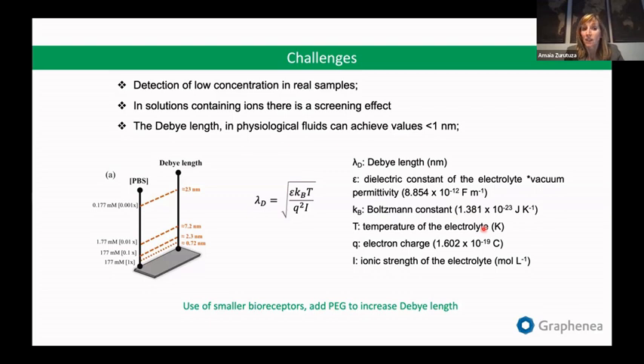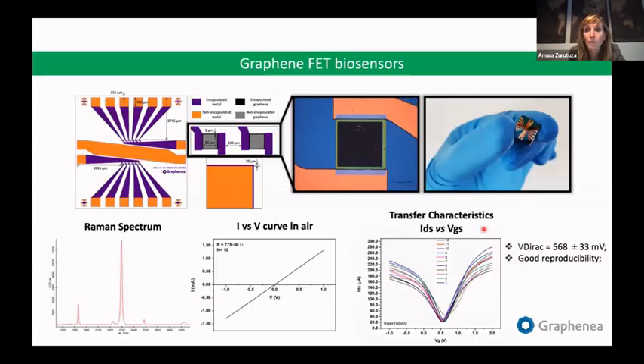So how can we overcome this challenge? One way would be to use smaller bioreceptors. Typically, antibodies are really, really large. So by replacing an antibody with an aptamer, we can make it smaller and be within this Debye length. Another way of increasing this Debye length is by adding, for example, polyethylene glycol in order to stop the screening of these charges. So there are ways of overcoming it, but it's something to keep in mind, especially for biosensors.